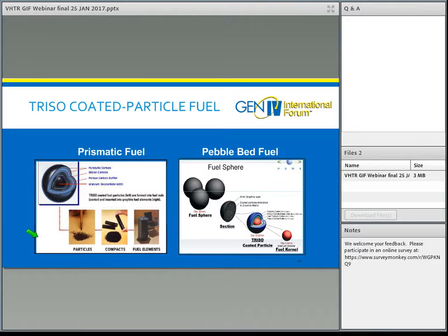So looking first at prismatic fuel, what we end up with are these tiny particles. They are the size of a pencil dot. And in constructing an actual reactor core from this, you would have billions of those particles making up the entire fuel. You take the particles, combine them with a graphite matrix and press them into these compacts. It's a little bit larger than a pencil. It's similar to a fuel element or a small fuel part in a light water reactor, but with much less content of the fissile material. And then those compacts are loaded into holes in a larger fuel element.